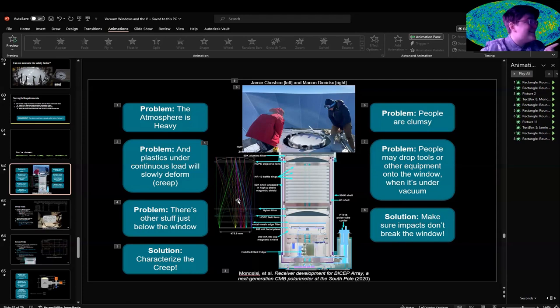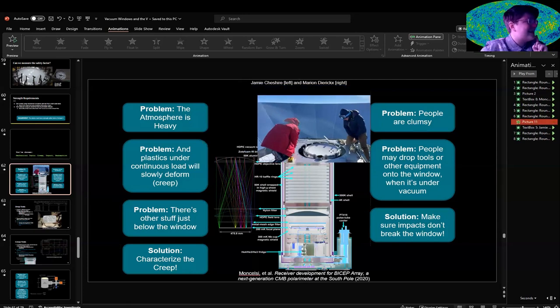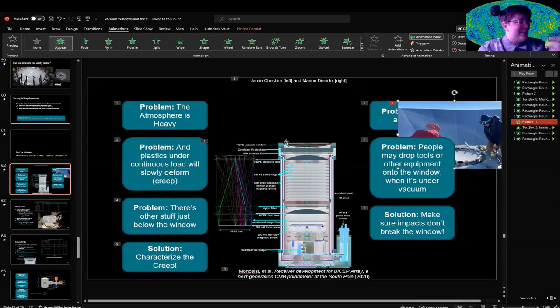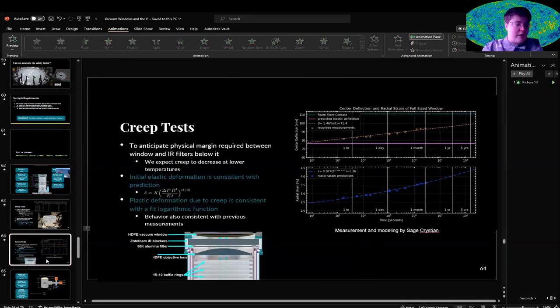As for creep, we do worry about the creep on the window. And that's because, I'm just gonna move this, we have stuff directly below the window. And the window is really thin. So we have these infrared blockers, which are made of Zote foam, right below the window. And we don't want the window to creep into that. So we have done very long creep tests for about a month, and the creep of polyethylene is pretty well known, so we expect that the fitted deflection and the fitted radial strain should remain consistent. And the student that I had who was working on this, Sage Crystian, he calculated with the appropriate offsets and stuff, because we also have offset the window slightly with a ring.